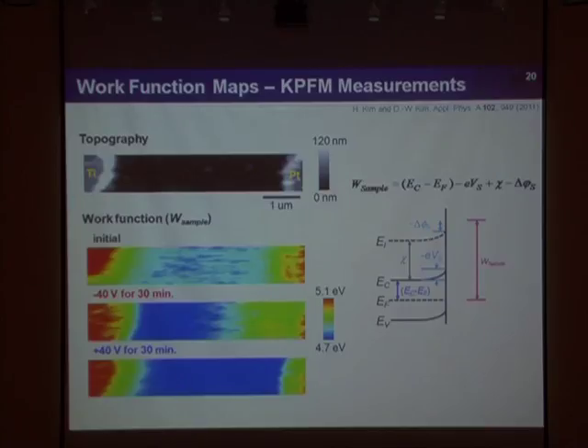But that is due to oxygen adsorption. I already talked about how adsorption is an important trap contribution in the previous PT-STO cases. Also here this portion is very important. If oxygen is adsorbed at the surface of titanium dioxide, it's pretty well known that the oxygen will take electrons from the TiO2.